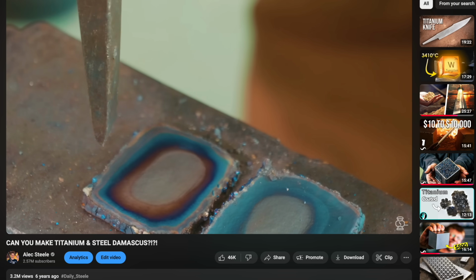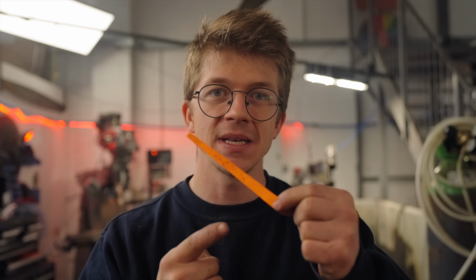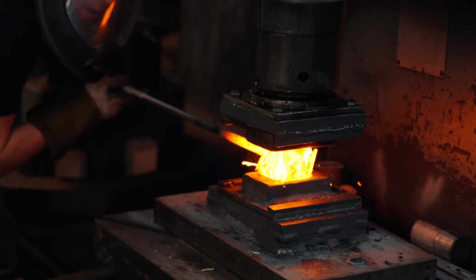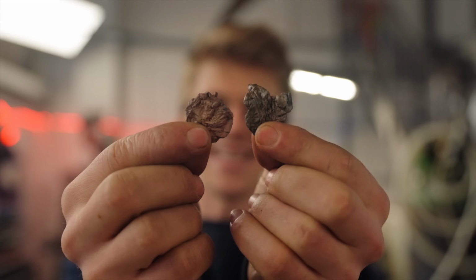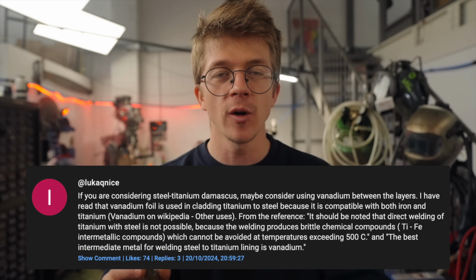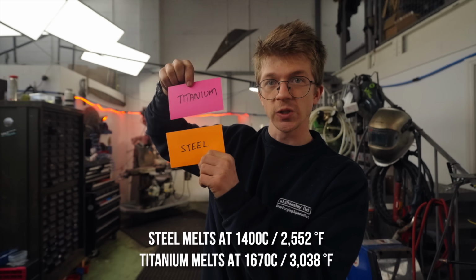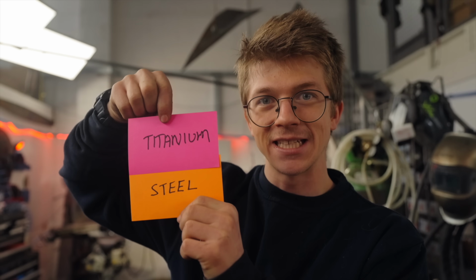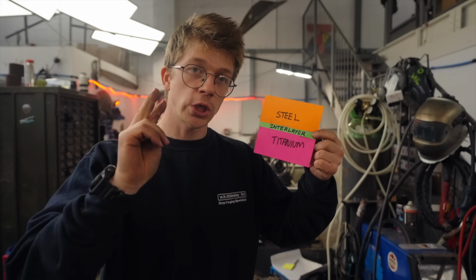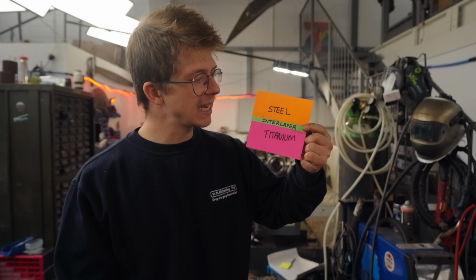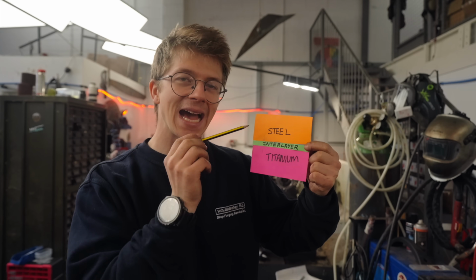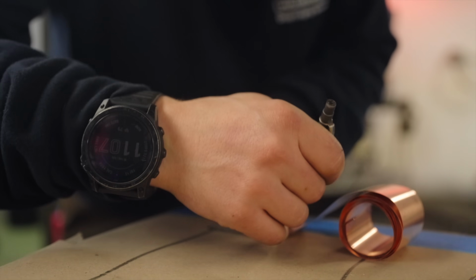6 years ago, we tried to bond titanium to steel and we saw it fail. You have seen the TiFe intermetallic compound because that is exactly what we saw when we had our squirting incident in episode 1 of Titanium Damascus. What came out is TiFe, and it was thanks to your help in the comments that we figured out what on earth this stuff was and why it was liquid. This stuff melts at like 1050 degrees Celsius, and so even though those 2 materials melt at a much hotter temperature, once those atoms have reacted together, they melt lower and out they squirt. And so the 2 key variables that we're going to be experimenting with today are the material choice for the interlayer and its thickness. So let's show you what we've got.